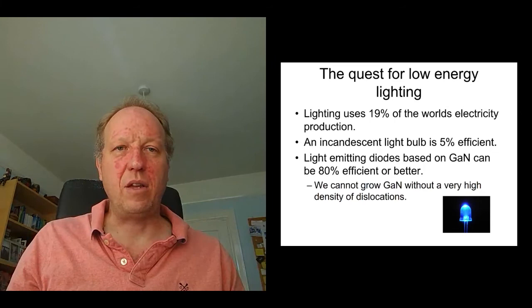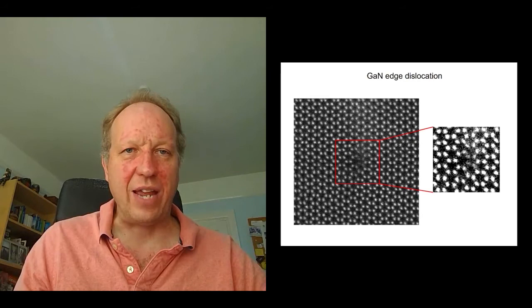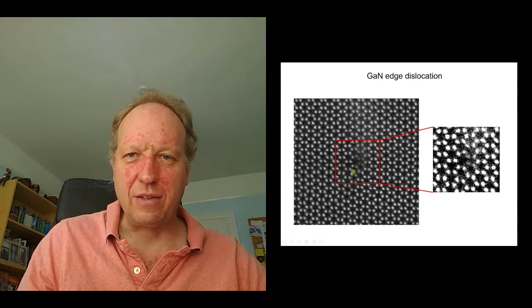And they can lower the efficiency and the longevity of the light emitting diode materials. So studying these dislocations is of great interest. So here's an image that I took of one of these dislocations in gallium nitride. Gallium nitride is a hexagonal, has a hexagonal crystal structure. You can see how the atoms line up into these lovely little hexagon patterns. And if you look in here, here's the dislocation core right here. And you can see the lattice has been disrupted.